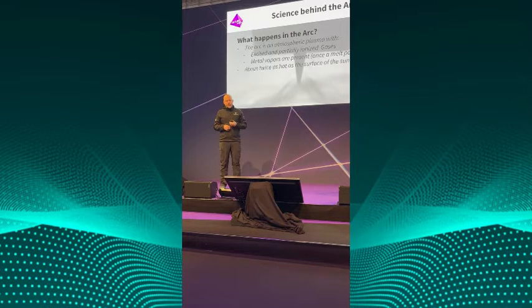As soon as you have an established weld pool, you have metal vapors present. And those two facts are causing a lot of trouble in the science, because it's super difficult to understand and simulate the mechanisms behind it. Also very interesting, the arc is about twice as hot as the surface of the sun.